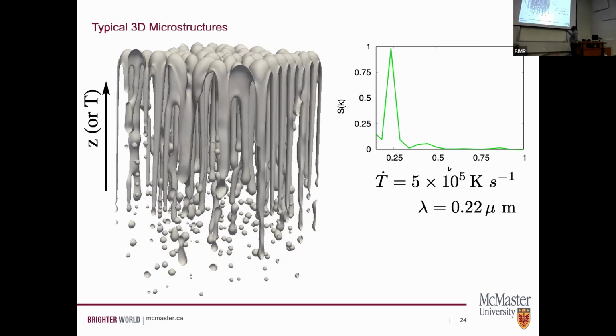So in 3D, we find for somewhat of a similar cooling rate that our spacing is somewhat smaller than what it was in 2D. And again, our explanation here is that in 3D, you have other factors, particularly diffusion doesn't work the same way in 3D as it does in 2D. So in 2D, it's restrictive, in 3D, it's not. So in 3D, diffusion occurs in all directions, which tends to stunt how these fingers emerge from the solid.